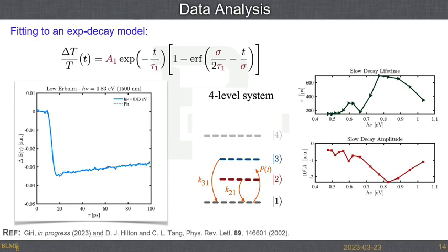That actually is data that we feed back to Delaware, and they look at how they're engineering the erbium arsenide nanoisland structure in this material to be able to shorten this particular lifetime. According to Joshua, it means he needs to change the density of the erbium arsenide nanoislands that he's fabricating, but we don't have that sample yet to be able to test that hypothesis.